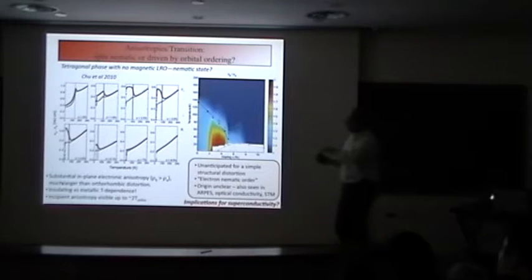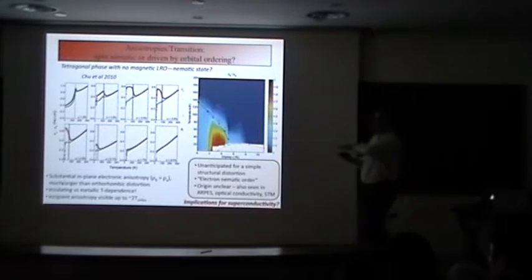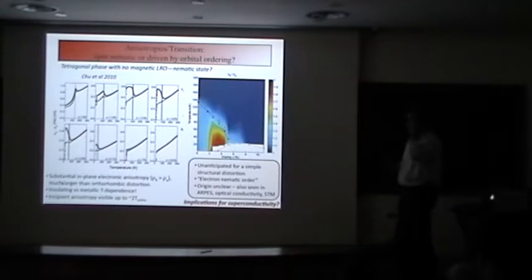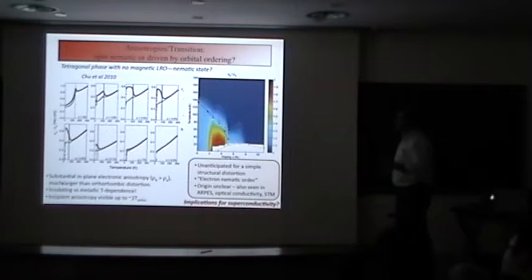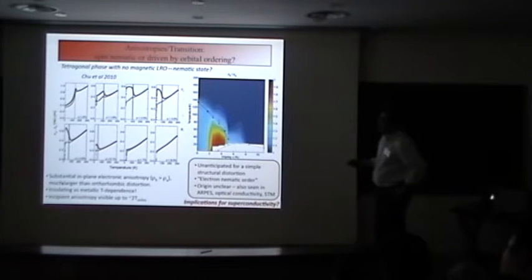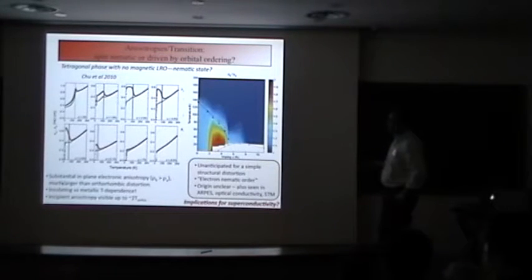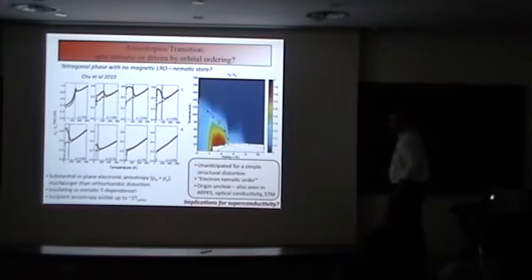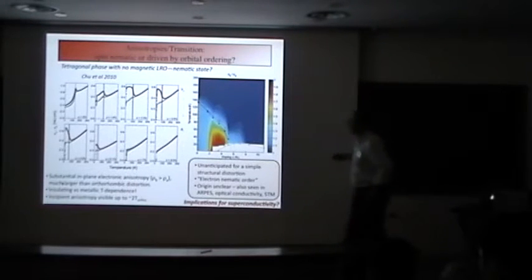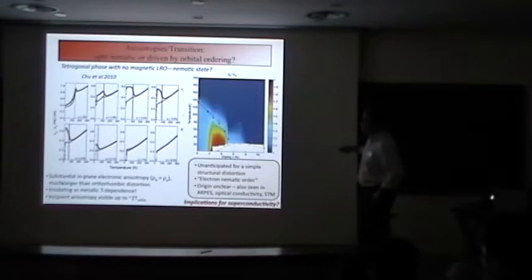By using a particular clamp to get rid of twins and looking at a single domain of magnetism, they plot the resistivity along the A direction and the B direction as a function of doping and temperature. What they see is, as you cross this line down near the antiferromagnetic compound...